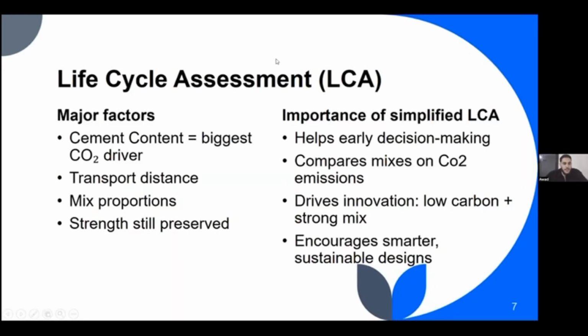Several major factors affected our simplified LCA outcome, starting with the type and amount of binder. Since cement has the highest carbon footprint, reducing its percentage significantly impacted the results. We replaced it with slag and silica fume, which are low-emission byproducts that helped lower the global warming potential. Another big factor was the transport distance of materials. Local sourcing can reduce emissions while importing materials increases them. Also, the mix proportions, especially how much binder, water, and aggregate we use per cubic meter, affected the CO2 total. Finally, even though it's a simplified LCA, functional performance matters too, by maintaining the strength of our mix.